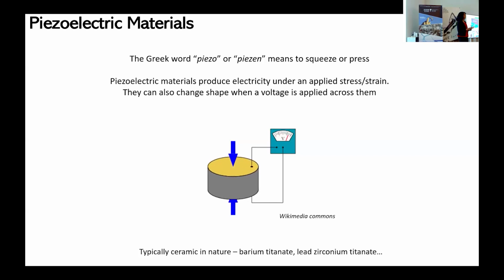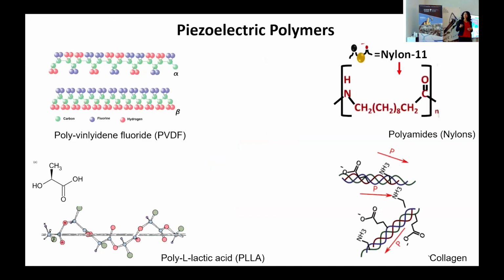But from a mechanical energy harvesting point of view, these ceramics are not necessarily the ideal candidate, because as you can imagine, I'm talking about something which is being squeezed or strained repeatedly over and over again. And ceramics are stiff. Mechanically, they're prone to failure. So this is where I came across another class of piezoelectrics, namely piezoelectric polymers, which also exhibit this effect, but they are generally much poorer counterparts to the ceramics. So their so-called piezoelectric coefficients are often lower. But they have all the advantages that I would like for a mechanical energy harvesting device, namely, they're flexible, they're robust, they don't contain lead, which a lot of the common piezoelectric ceramics do. So lots of things going for them.